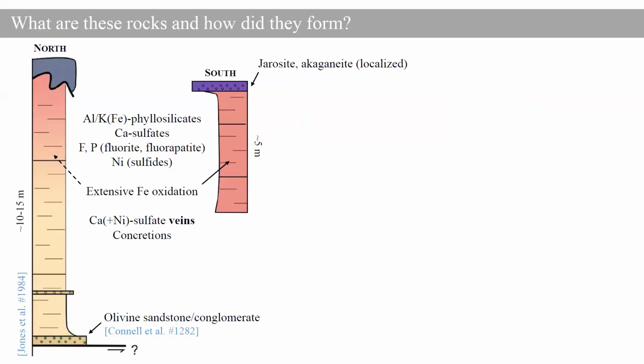So to summarize this SuperCam view, in this unit, we see a fine-grained bedrock that is mostly composed of aluminum, potassium-rich phyllosilicates. But we also see some calcium sulfates, some fluorapatites and fluorite, and strong enrichment in nickel. This bedrock is also enriched in ferric oxide, especially in the south, and it is cross-cut by sulfate veins and has concretions. And in the upper part of the stratigraphy, we are seeing that the rocks are capped by a more massive iron-rich bedrock with at least some jarosite and akaganeite.